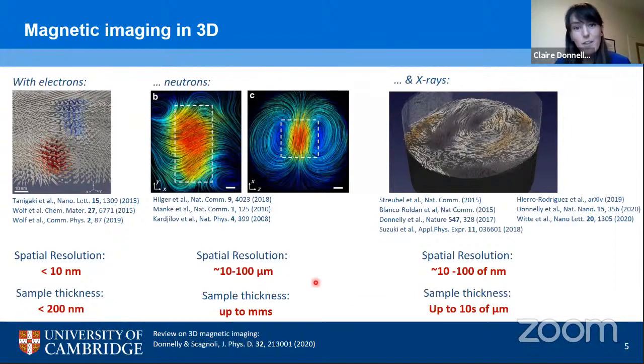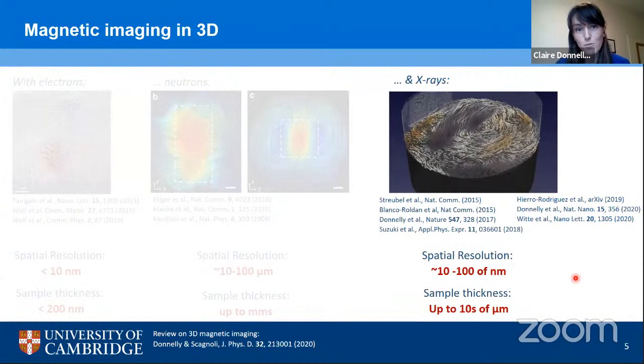Now, neutrons, we have the opposite extreme. We have lower spatial resolution, but we can look at much, much thicker samples. And with X-rays, we kind of combine the best of both worlds. So we're able to retain this high spatial resolution on the order of tens of nanometers that we have with electrons. But by going to higher energy X-rays, we're able to probe samples that are much thicker, up to tens of micrometers in diameter. And it's for this reason that we choose to use X-rays for our experimental investigations.